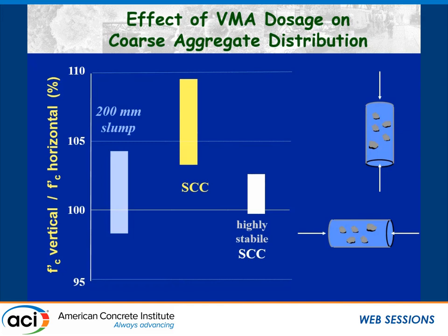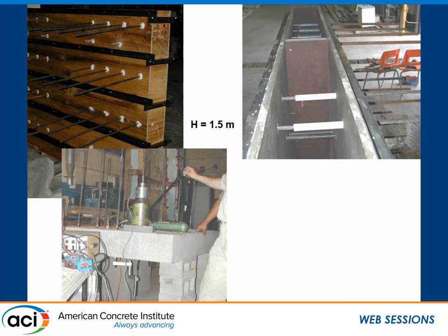Okay, we said we're going to talk about bonds. So you cast those concrete elements. In these experiments, we even have some pre-stressing strands. And then you limit the embedment lengths to about 2.5 bar diameter. You flip them, and then you do the pull-out test, and you measure the slip at the bottom.